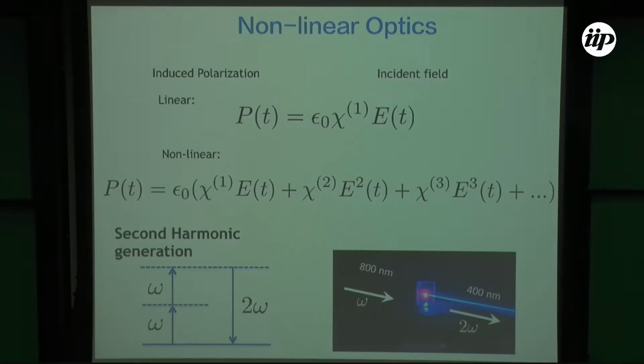Okay, so this was discovered in the 60s, just after the invention of the laser. Okay, so this was very important because with the invention of the laser, we have enough power in order to see these nonlinear effects. Okay. So just to show you, you use for example a laser with an 800 nanometer wavelength. So it interacts with your material, and then you have the emission of the second harmonic at 400 nanometers. Okay, that's twice the energy of the incoming light.